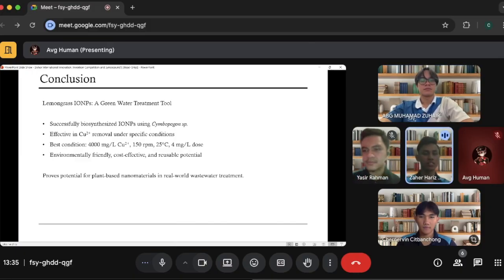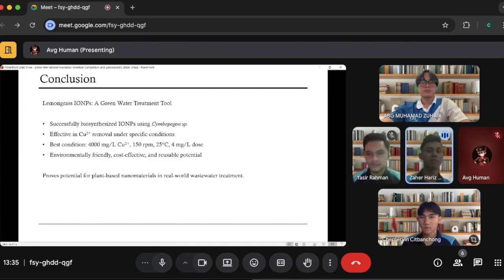To conclude, we successfully synthesized iron oxide nanoparticles using lemongrass extract via a green, cost-effective, and sustainable method. These nanoparticles showed excellent adsorption potential for removing copper(II) ions under optimal conditions, specifically at initial copper(II) ion concentration of 4000 mg per liter, stirring rate of 150 rpm, temperature of 25 degrees Celsius, and an adsorbent dosage of 4 mg per liter. This approach shows the feasibility of green synthesized nanomaterials to be used as adsorbents for heavy metal removal.